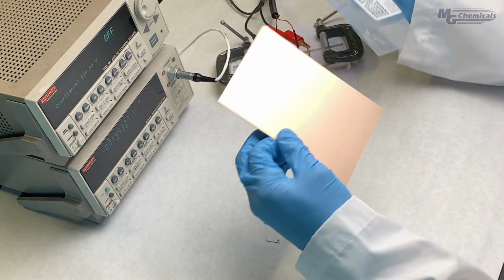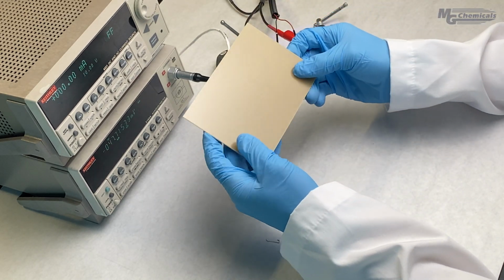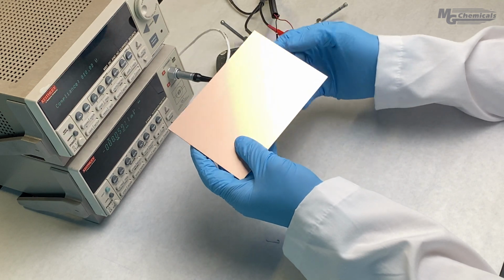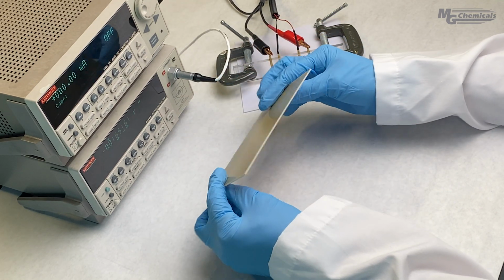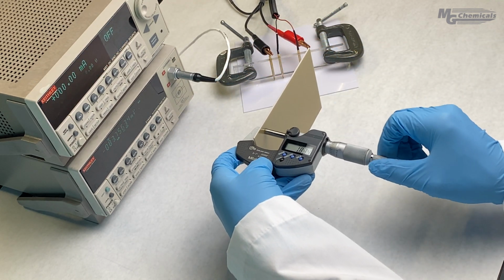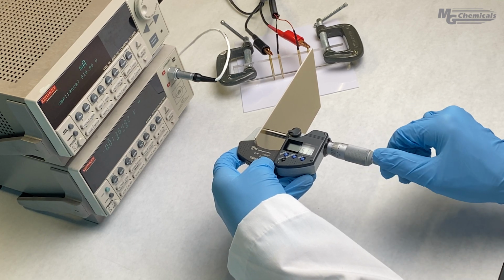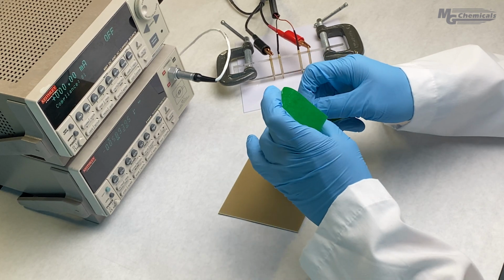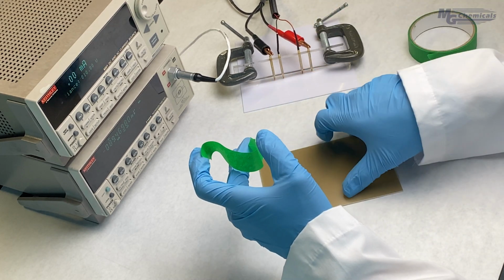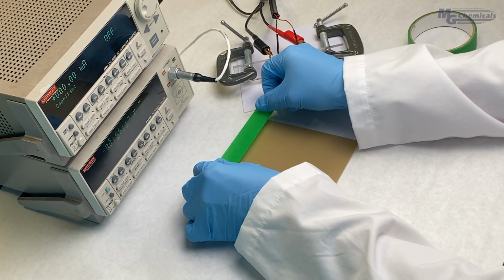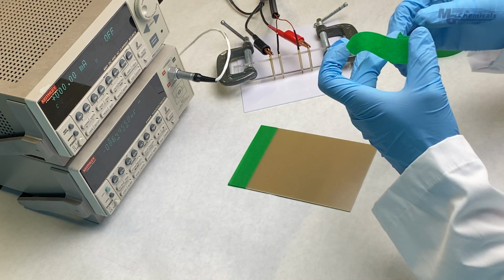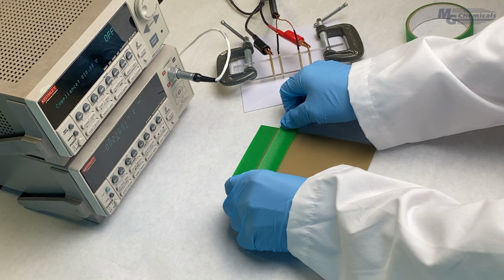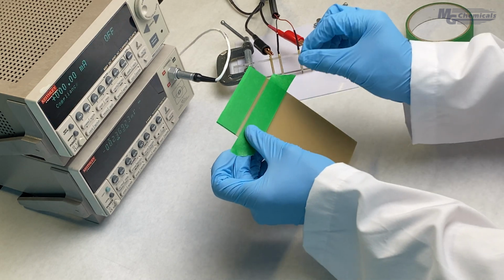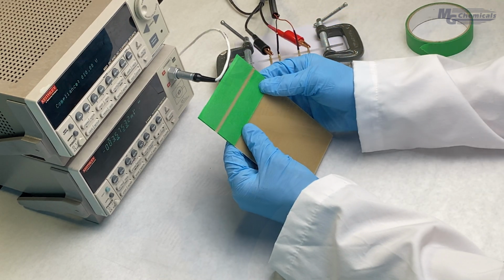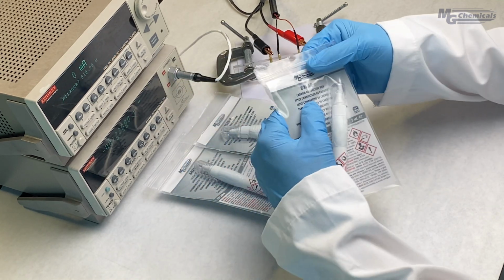To start, we have this solid piece of FR4 laminate board, but you can use another substrate. It just needs to be electrically insulating. First thing we want to do is measure the thickness of our substrate that's uncoated, and we'll show you why a little later on. Use painter's tape to section off clean, even lines, which product can then be applied to. Be sure to take caution when sectioning off these lines, as they will directly affect the resistivity calculations.